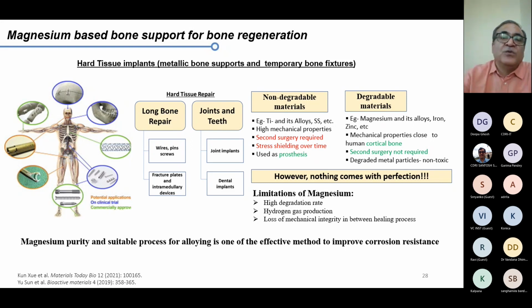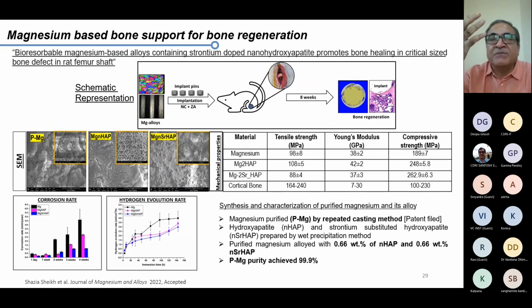We looked into one aspect which I just want to mention. Making a magnesium alloy is not simple, because it's not like any other type of metal. It needs an inert atmosphere. Having a complete inert atmosphere is considered very critical, because even if you have traces of oxygen there, it will catch fire. You will get oxidized magnesium.